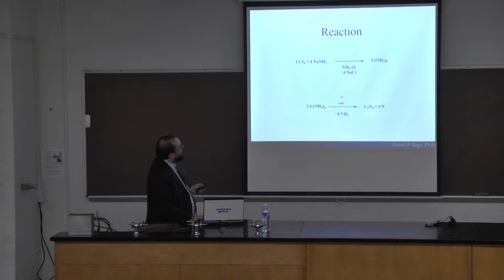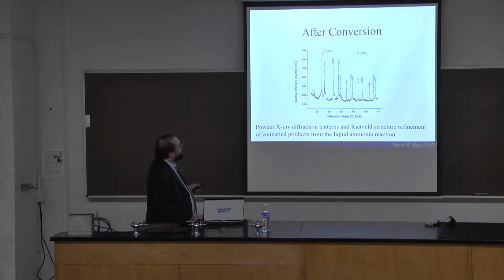So by following this reaction in this exact same way, what I ended up getting was uranium nitride. Now this is what's known as a powder X-ray diffraction pattern. So rather than having a bunch of nice little dots as in a single crystal, you have a bunch of small crystals all crushed up. So you don't get that nice pattern, but nonetheless, when you reflect off it, you're going to get certain angles that are going to reflect heavily, which is what we're seeing here, based on the overall angle of the beam and the detector.